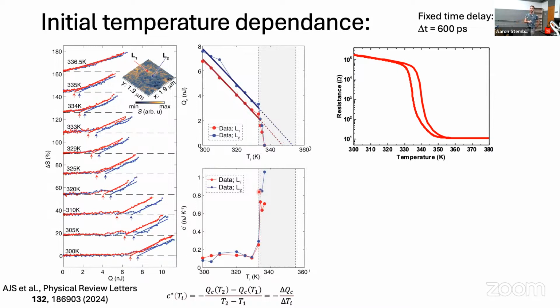We repeated all of these measurements at a neighboring location where we observe some kind of inhomogeneity. And notably, the fluence threshold is higher at this second location. However, this is essentially an offset; the actual change in fluence threshold as a function of temperature has a very similar slope at the two locations. And more notably, the temperature where we observe this kink, where the fluence threshold starts to decrease rapidly, or this quantity C star diverges, occurs around the same initial temperature. So this instability in the system seems to kick in at the same temperature at two locations where we observe an inhomogeneous fluence threshold.